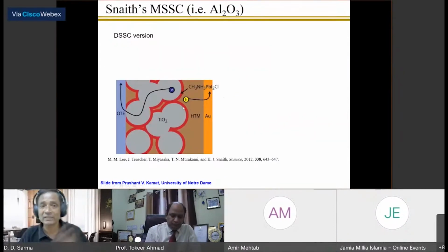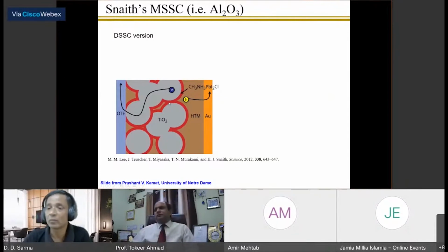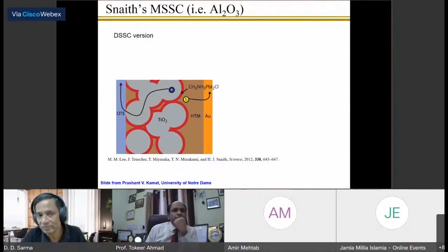Not only that, in this dye-sensitized solar cell that I talked about, the photoactive material which absorbs the photon is normally a thin layer. But the electron and hole that we generate are conducted, on one side, the electron by titanium dioxide, and on the other side you put another hole-transporting material so that they get separated, because in general the material does not have good mobility.